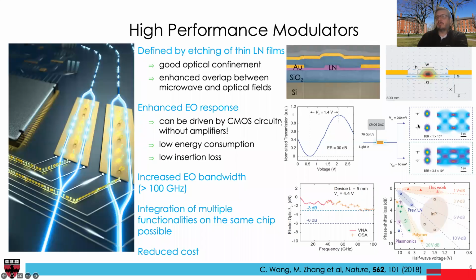This is somewhat old results, and we're going to go into details of it, but basically, what is shown here is a data rate of about 70 gigabits per second when the modulator is driven with as little as 60 millivolts of peak-to-peak drive. So this really low drive voltage reduces power consumption, but perhaps even more importantly allows you to drive these modulators directly using CMOS signals, which eliminates the need for RF amplifiers, which is great savings in cost, energy, and also space.